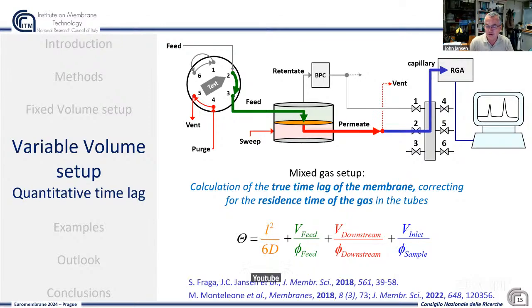And we found a way to quantify all that. We know the delay that's caused by the system, and then we can subtract the delay from all our measurements and finally come back to the time lag of our membrane, which then gives the diffusion coefficient, and that makes this system unique because everybody can measure a permeability. That's nothing really complicated. But if you are really able to measure the time dependence of your signal, then you can also get the diffusion coefficient of your gas through the membrane.